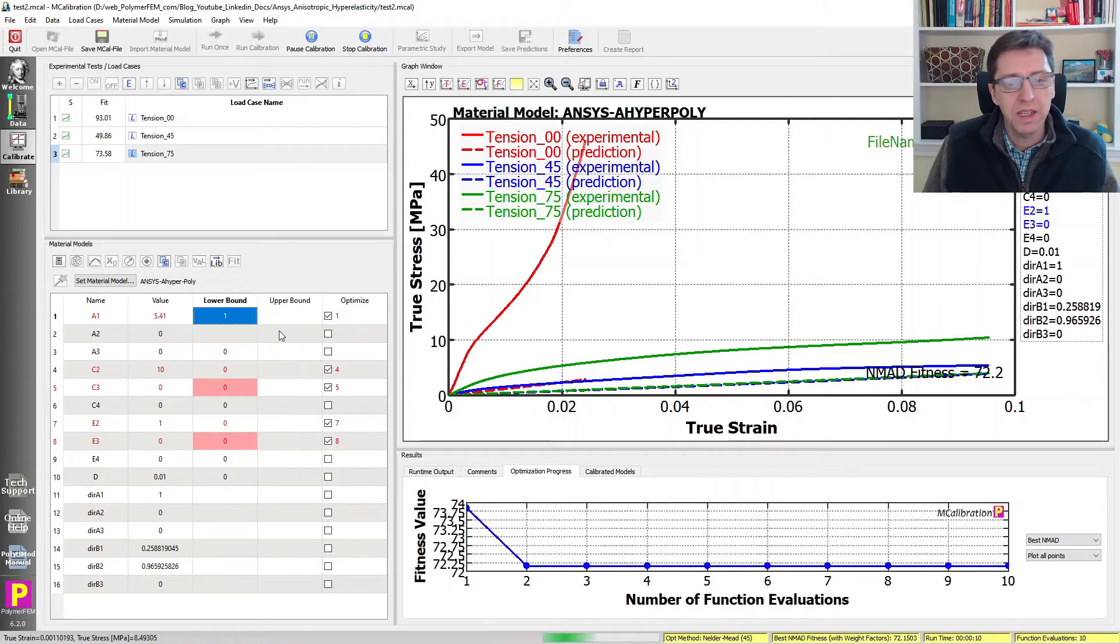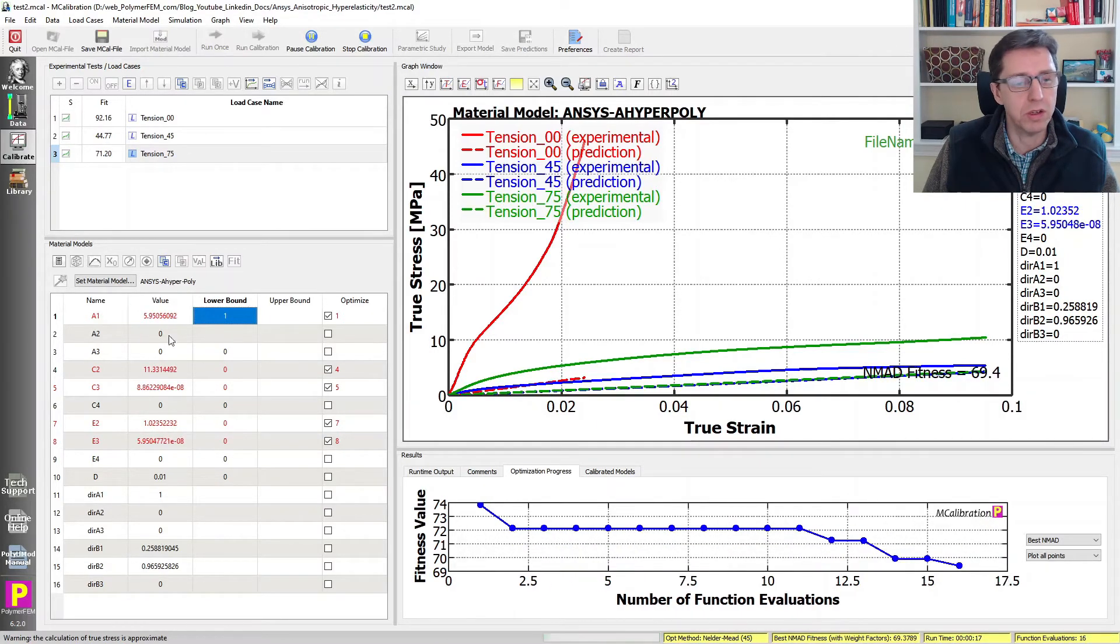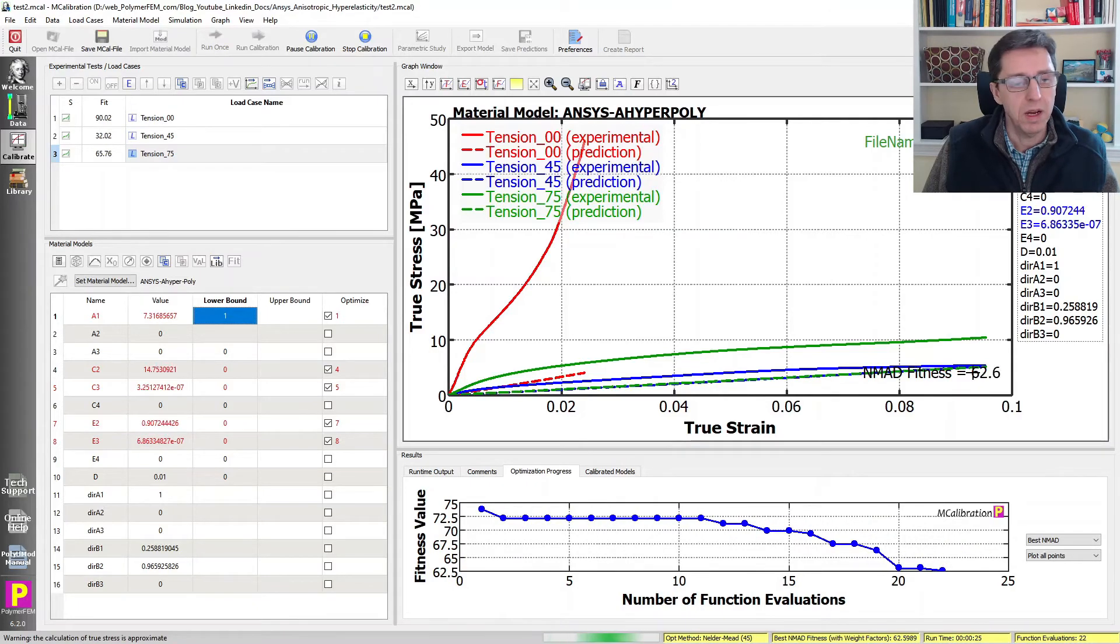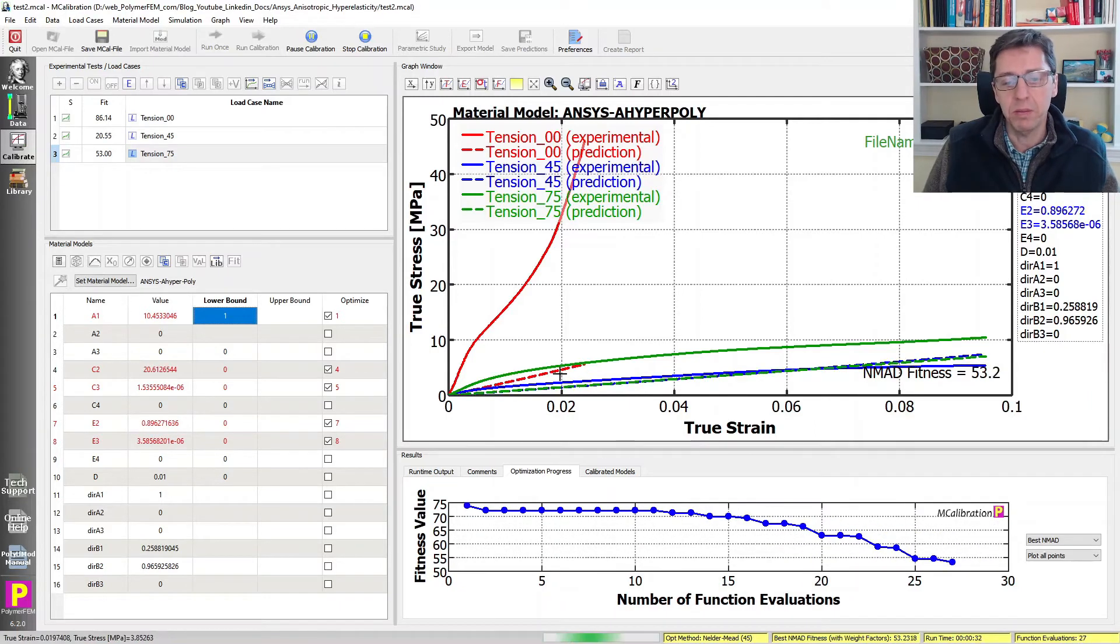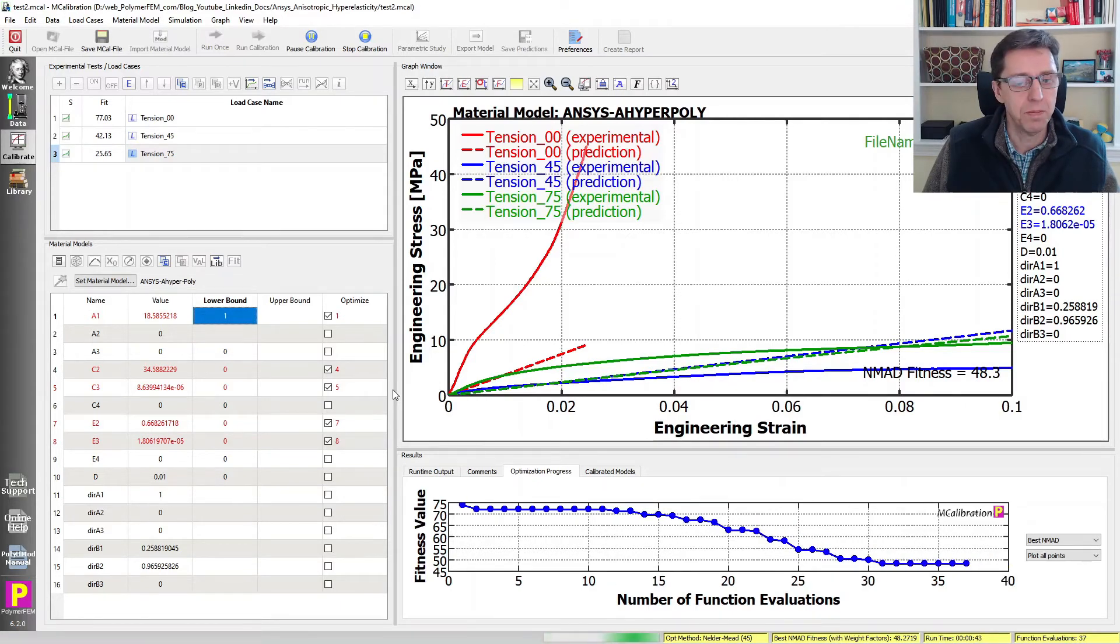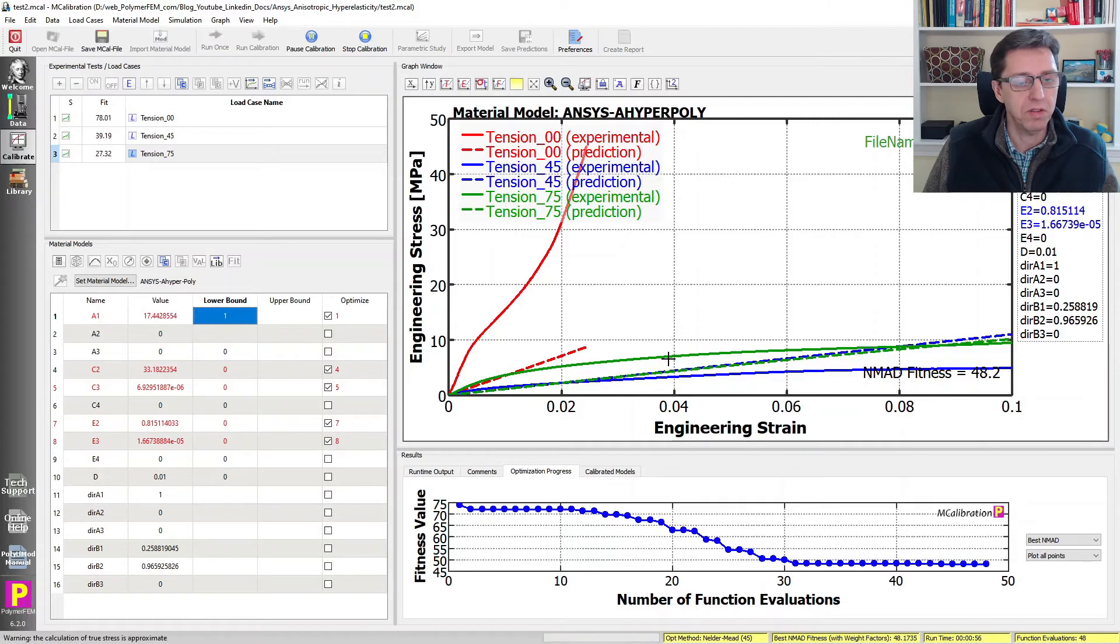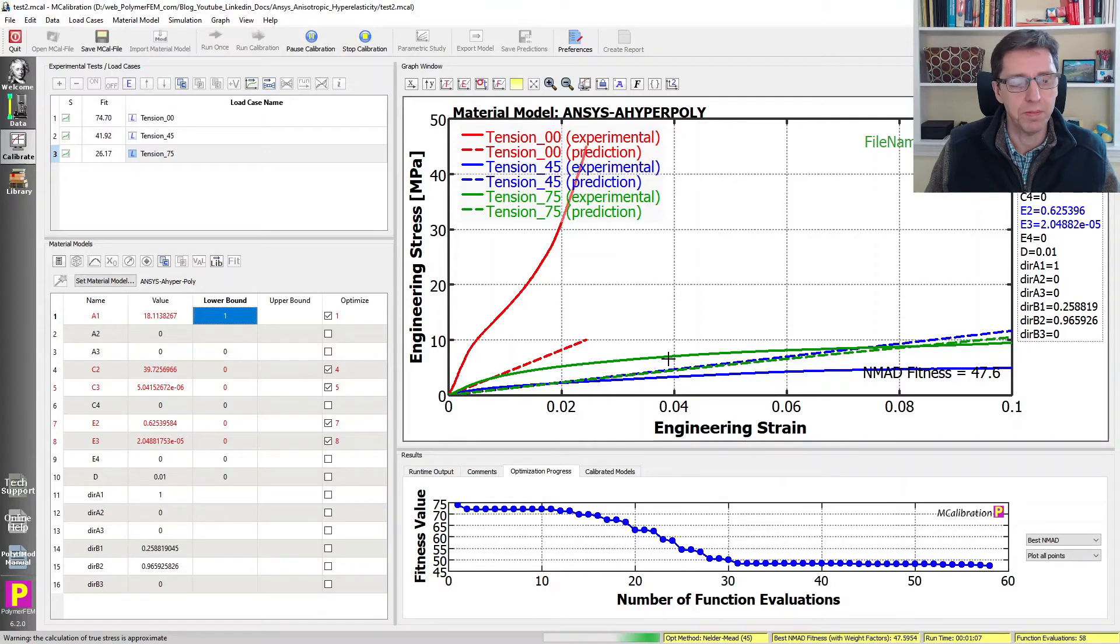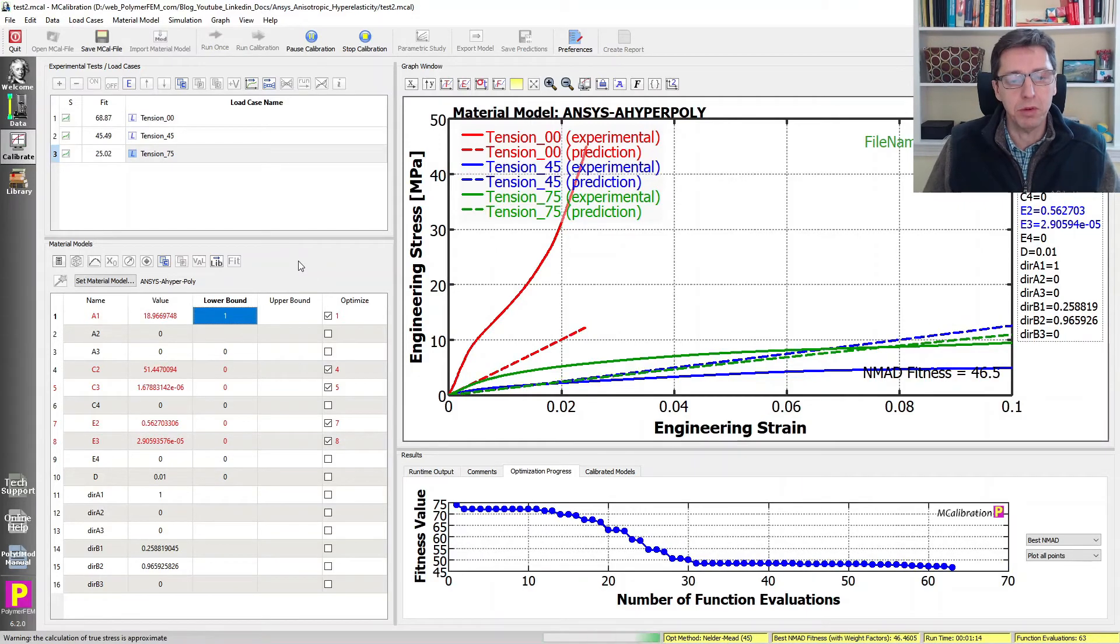I would think that the main issue at this point is that C2 needs to be much larger, C3 needs to be larger, and A may be actually good enough. Right now the stiffness comes mostly from the matrix. See, it's starting to increase C2 as we expected. That will make this red line go up much more for us. We can plot engineering stress strain because the experimental data was engineering stress strain. We want the 75 degree direction to be a little stiffer than the 45 degree direction. I think we'll get that if we just wait a little bit longer here as it moves through these iterations.